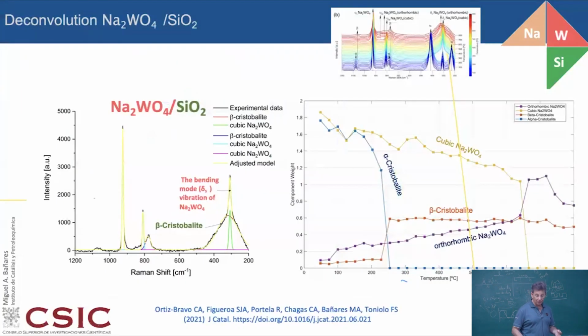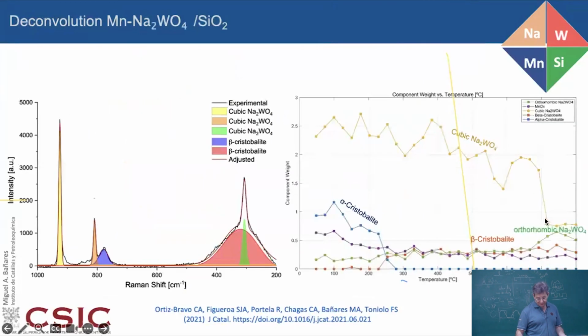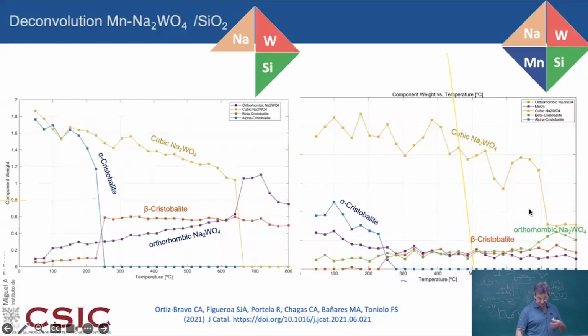You can integrate the different components and analyze the evolution of the different phases with Raman spectra during all this temperature treatment. You see a progressive decrease of the cubic sodium tungstate phase, which in the end is replaced by the orthorhombic sodium tungstate, and also, at a given temperature, the disappearance of the alpha cristobalite silica phase and the appearance of beta cristobalite. So you can monitor all these things. Here you have it for the manganese sodium tungstate with all the phases, including this beta cristobalite, which is a broadband. And then you can see the evolution and the changes with different temperatures and different compositions.